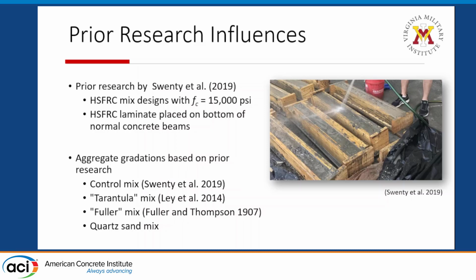For the mix development, I used their mix proportions for their HSFRC and changed the gradations of the fine aggregates used in the project, with these gradations that you see at the bottom here. The control mix was basically what they used. This was the baseline that I was trying to bolster the strength of. Then there are three experimental mixes: the tarantula mix, which was from Dr. Ley, the Fuller mix using the Fuller equation, and a quartz sand mix, where I basically just found quartz sand and used that as the aggregate to see what would happen to the compressive strength.